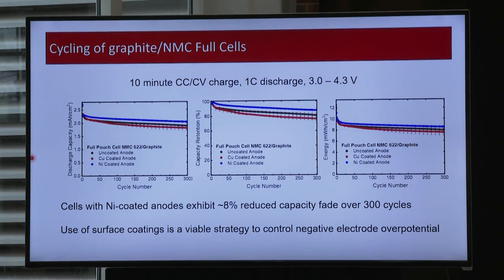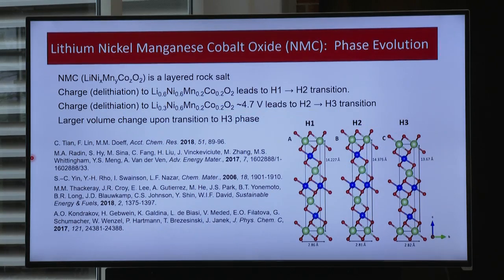We then moved on to assembling full-scale cells. These now aren't tiny lab cells, these are pouch cells, where we had an NMC cathode, which is a typical cathode for electric vehicles. We had graphite anodes that we either plated or did not plate with nickel or copper. And over many cycles, we've run up to 300 cycles, we get significantly improved capacity retention with our metal-coated electrodes. We're excited about this because this is a technology that can be implemented with existing manufacturing processes. So let me move on.